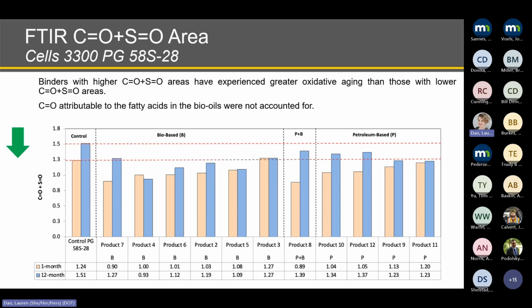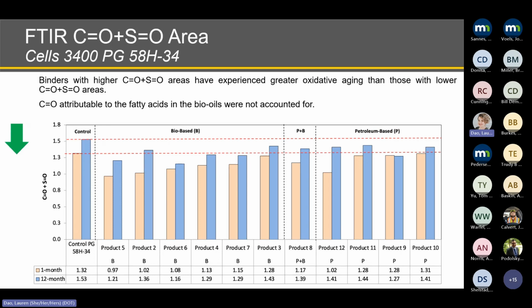So you can see that with this approach, we can capture that all of the products are reducing the aging of the binder between 1 month and 12 months of field application. Same evaluation performed here for the PG binder 58H-34, and we can see the same trend.